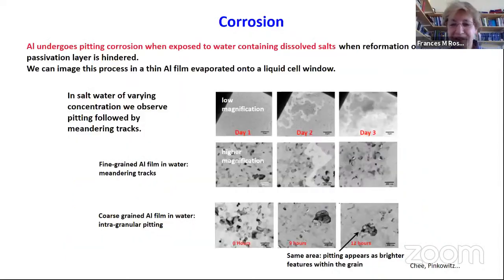Okay. All right, so I talked a lot about nucleation and growth and matching with growth models. I want to briefly cover a few other things that liquid cell microscopy has been used for. One of the most important things is corrosion. There's a number of groups studying this. These images are from one of our experiments evaluating the corrosion of aluminium films in salt water. These are slow experiments, but you can see the pitting corrosion followed by the formation of tracks beneath the oxide. And you can see intragranular pitting in some of these experiments also.